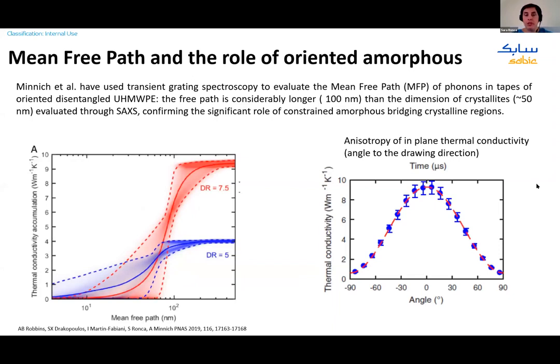We did some studies in collaboration with Minnich at Caltech, and they used transient grating spectroscopy to evaluate the mean free path of phonons in tapes of disentangled polyethylene. And what they found was that the mean free path of phonons is considerably longer, about 100 nanometers. So it's longer than the actual dimension of the crystallites that we evaluated through SAXS to be about 50 nanometers. So this confirms, of course, that there is a significant role of the constrained amorphous phase that bridges the crystalline parts. And they also found experimentally how deeply anisotropic the thermal conduction is in these oriented tapes.